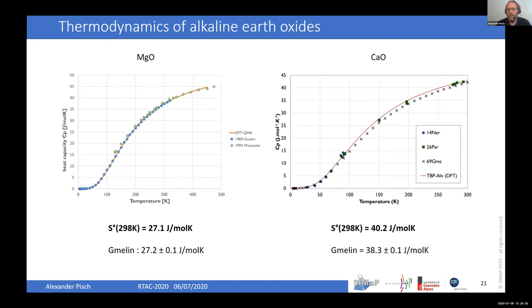And you see for calcium oxide, we have a shift. The values from Gmelin, which are the crosses, are way below the values we calculate. And therefore, the calculated entropy of 40.2 joules per mole per Kelvin is higher than what Gmelin derived from his data. So the question is, are our calculations wrong? Is the method not good enough to describe the data for lime? Or may the problem be in the measurement?